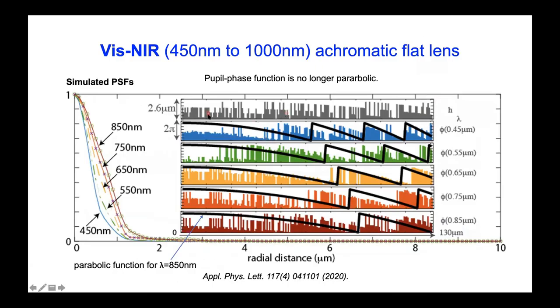So here, what we're showing in the insets, just for a second, the top inset is the geometry, so the radial distribution of the rings, the heights of the rings, and the different colors here represent the phases at different wavelengths, going from 450 nanometers all the way to 850 nanometers in the near infrared.